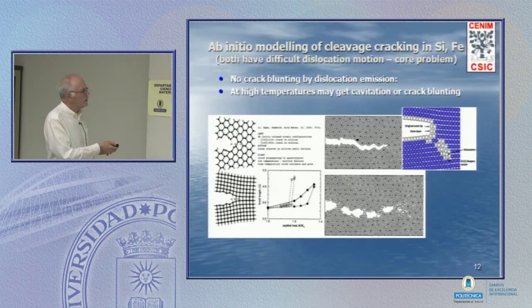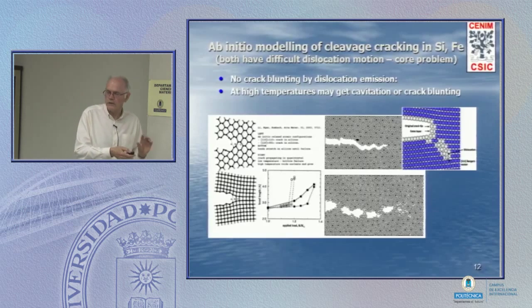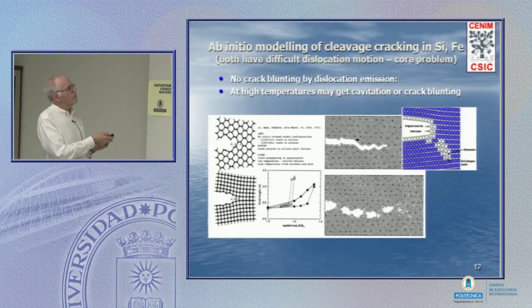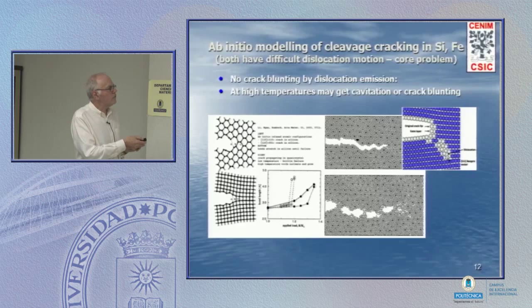Now in the ideal case, a cleavage crack is atomically sharp, and we're going to break bonds one by one by one as this cleavage crack propagates forward. So it's very brittle. That's what silicon is, that's what iron is. That's what intermetallics tend to be. So here we've got some ab initio modeling showing what may happen at the crack tip.